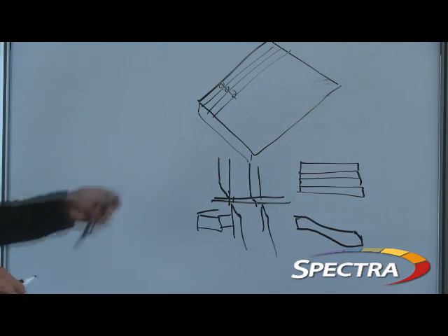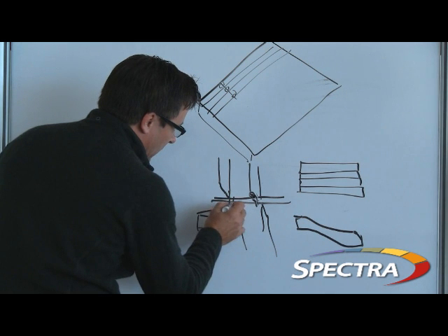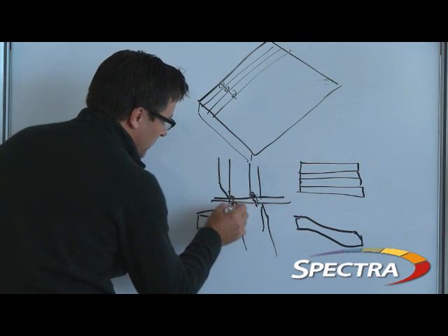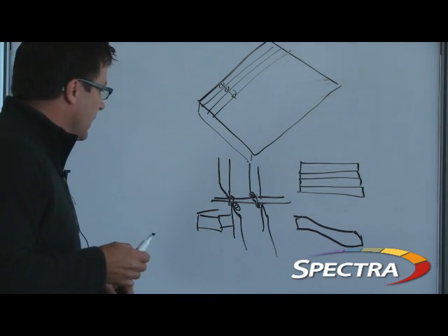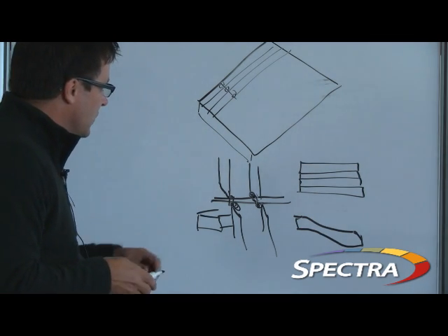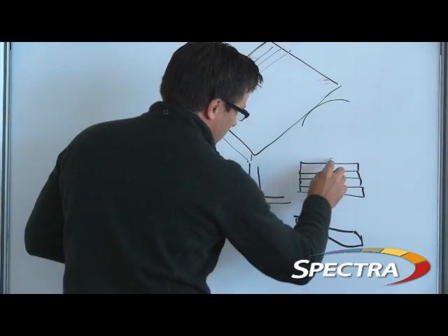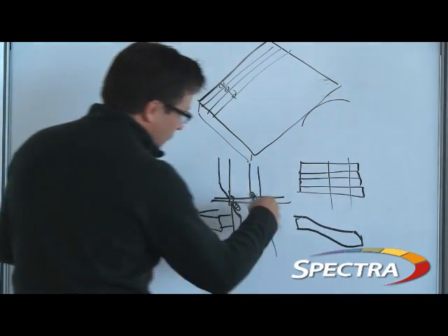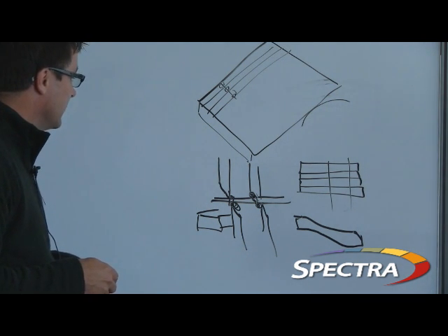So when you have a piece of curved media, the other thing that's going to happen there is a little bit of debris. When this cutter comes in here, it is going to pop up and build up here, and a little bit more debris here, and possibly a little here and a little here. And that debris is called slitting debris. So you take a new piece of media, you've just cut it. The next thing they're going to do is they're going to run it past a cloth under here. This cloth is basically running right here, and it tries to clean this slitting debris off the media. It's a very soft process.